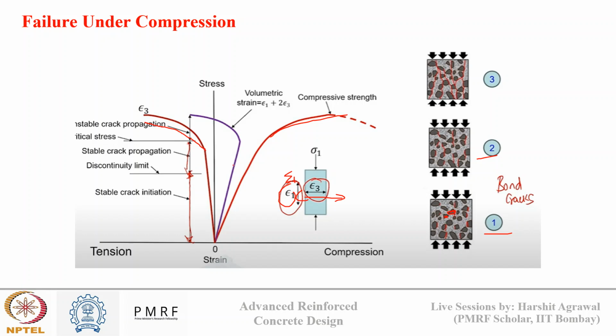However, if you see the volumetric strain, it is positive for the first two phases till here. And when the crack propagation becomes unstable, when these cracks have already connected and are able to form a failure plane, the tensile stresses start to dominate, and we see a shift in the volumetric strain profile from positive to negative until the failure occurs. And this justifies the failure pattern that we observe in concrete, where when we test concrete in compression, we see that failure occurs from this side due to bulging of concrete from here. That is due to the tensile stresses generated when the crack completely connects.